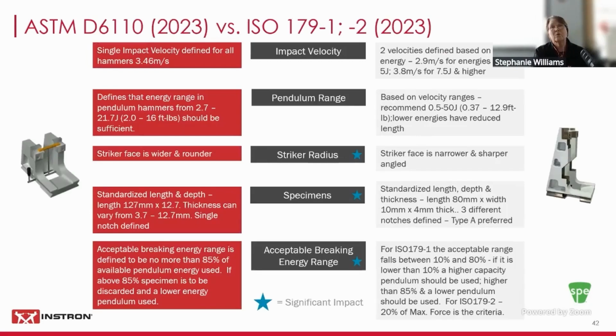So now I want to just do a quick comparison here between the standards. I've highlighted with the little blue stars where we see some significant impact that can happen. As we see impact velocity, ASTM has a single velocity, ISO 2 velocities depending on the impact capacity of the hammer. Pendulum range, so hammer range, ASTM actually defines it as being 2, 4, 8, and 16 as being sufficient to test polymers.